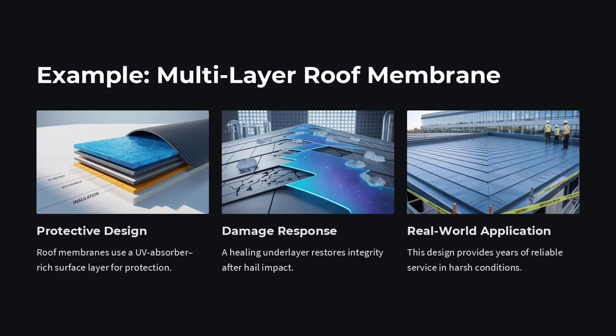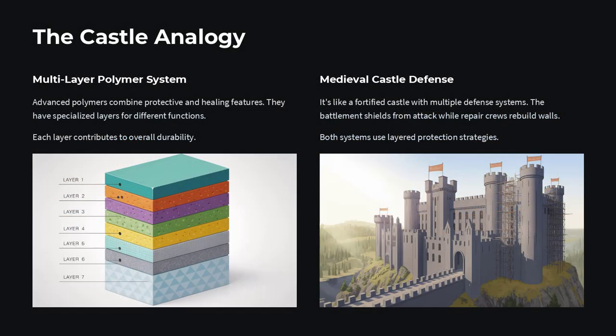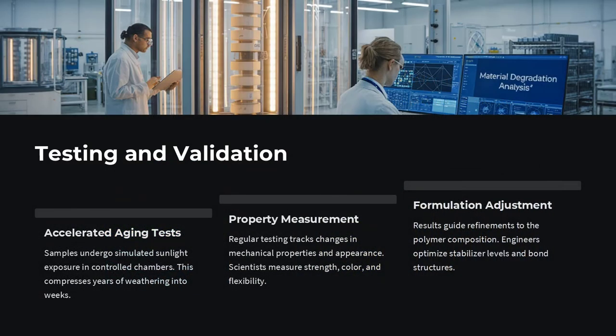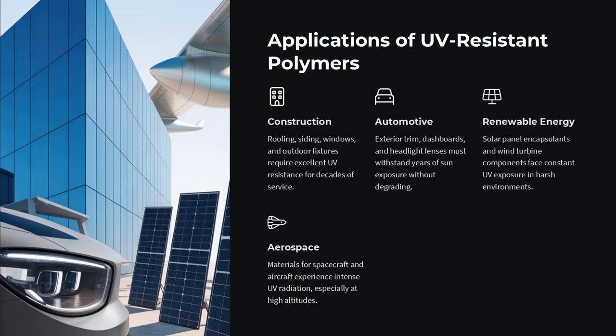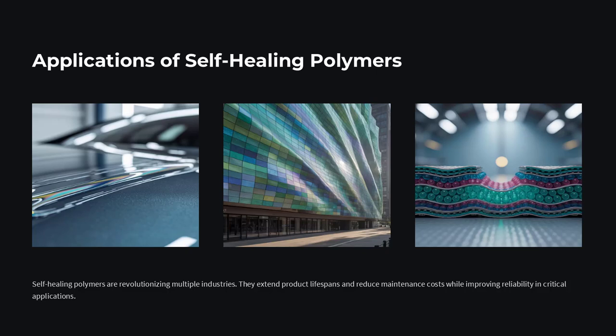Yes. Researchers have developed coatings for cars and electronics that self-heal minor scratches when exposed to sunlight. One example involves a polyurethane with special fluorinated side chains that soften and move slightly under UV light, sealing over damage. Another material developed for aerospace uses light to trigger a localized chemical reaction that fills microscopic cracks, preventing them from spreading into larger fractures.